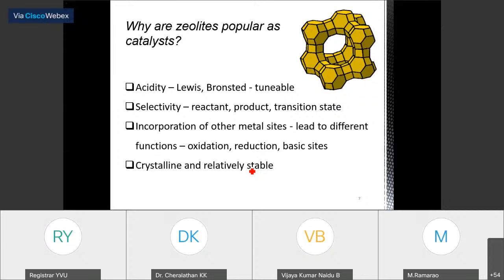Zeolites have acidity. They have acid sites. So typically, if you say the name zeolite, it is known as a solid acid. They have Lewis acidic sites and Brønsted acidic sites. And the beauty is that these Lewis and Brønsted acidic sites can be tuned by modifying the silicon ratio, or by modifying the cation. We can play with this acidity, and it is tunable. That is an advantage of this solid acid, zeolite.